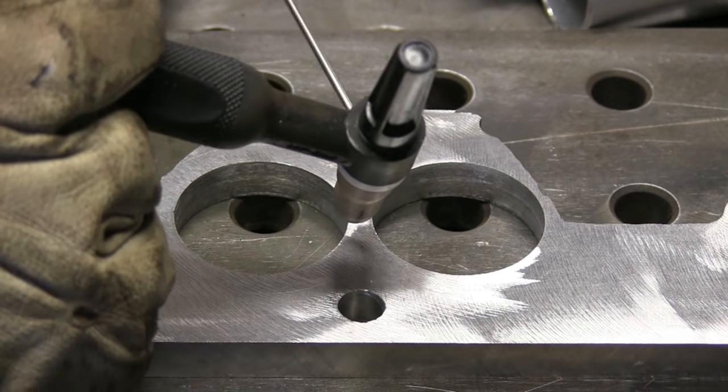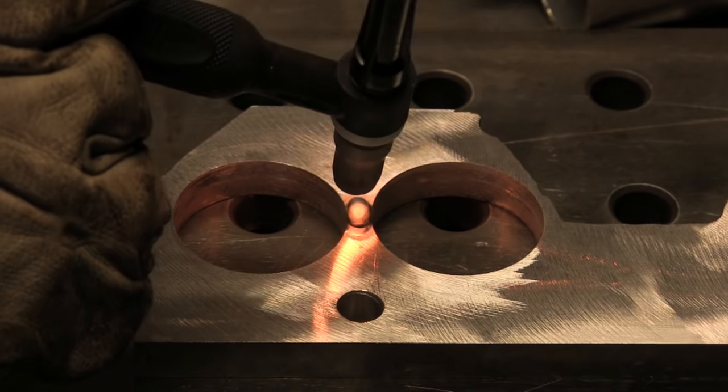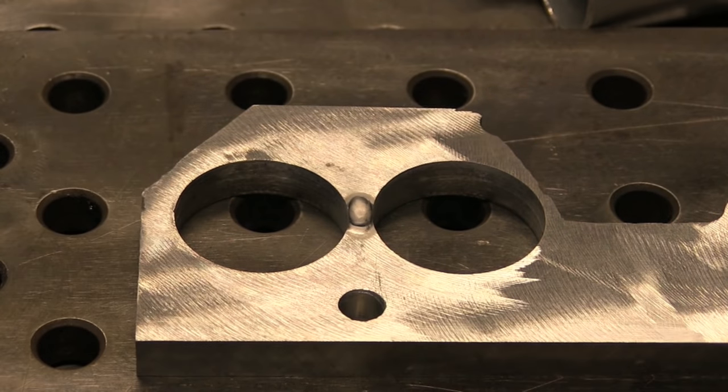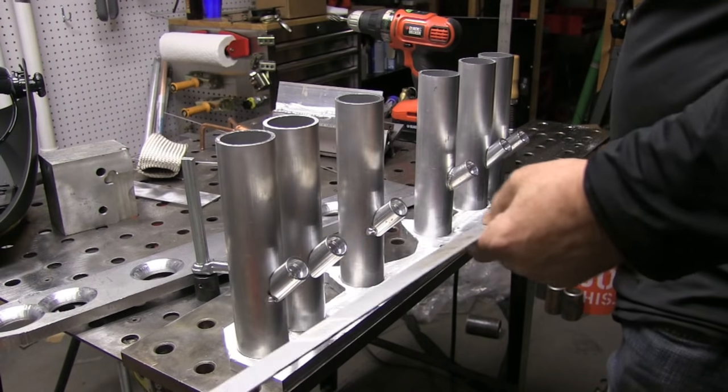So what I'm going to do is I'm going to add just a little pad here of weld. Weld metal 4043 weld metal melts at slightly lower temperature than most of the base metals that you would weld with it. This is 6061 base metal and the 4043 has got a little silicon, 5% or so silicon in it and so it just melts slightly lower. So my thinking is if I get a little pad here already it's just going to help me to get the weld all the way up in there and I forgot to do the other end of it so we'll be able to compare which one does work better.